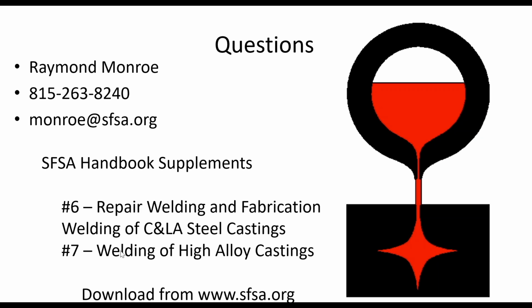We do have one question that came in. So what's a good metric to gauge whether production welding is overused? Foundries internally use the pounds of weld rod per ton of material shipped, but that really is an internal metric that depends on the kind of product you're making. And so it can be relatively high if you're making pressure containing parts, and relatively low if you're making simple parts. And so that's the typical metric that people would use, is pounds of weld rod per ton of casting shipped.